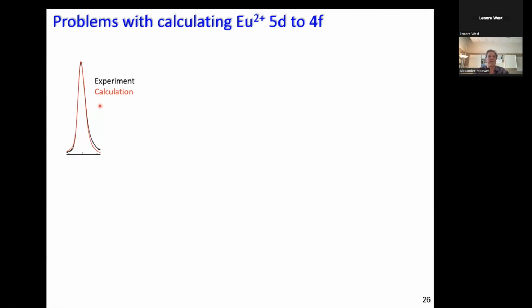We have one peak measured, the black curve, and we have one calculation. The problem is that the absolute height of the peak, in other words, the number of outgoing photons, is nothing you can ever really correlate in absolute numbers with your experiment. There's always a proportionality factor because you can neither measure nor calculate absolute photons. So that should be clear. Anybody who's ever done a spectroscopy experiment knows the height is always scalable. There's always a proportionality factor between experiment and calculation.